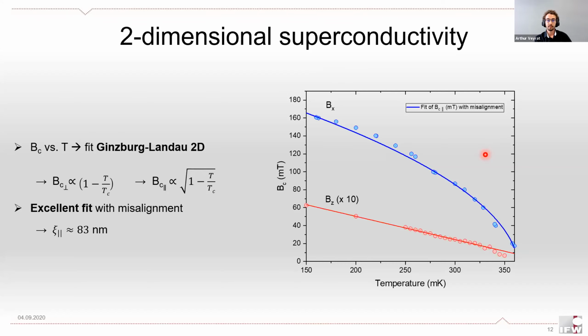So there is something special for this particular thickness, or not? I think this sample is quite at the frontier of thickness, in that our thicker sample is not displaying 2D superconductivity. I am not sure if we expect something drastically different for thinner samples. I think thinner samples should also display this sort of behavior, perhaps even more exacerbated. So it's a technical point, right? Yes. Also, trigonal platinum bismuth 2 is actually quite a soft material with weak in-plane strength, so it tends to break in tiny flakes rather than exfoliate very well. This is why it has taken us some time to study thinner structures.